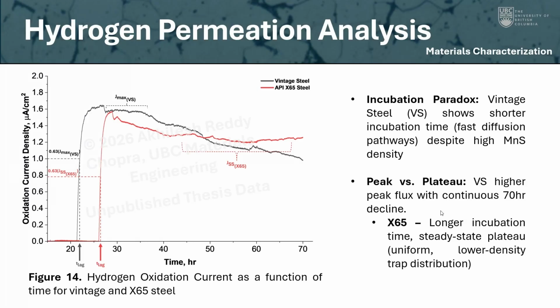And this suggests that the vintage steel has short circuits or fast diffusion pathways initially, allowing hydrogen to suddenly pass through that steel. And that is, again, likely due to the morphology of having those elongated stringer inclusions, or also being heavily banded. If you have that banded ferrite pearlite in between, essentially those interfaces, hydrogen can pass through.